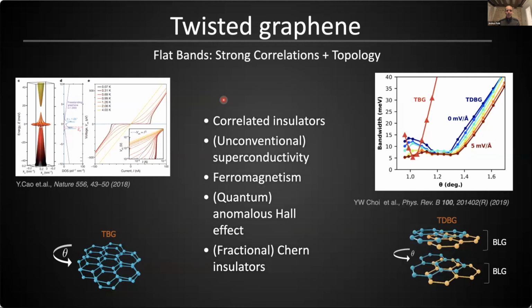But the special feature of twisted double bilayer is that because you don't have simply a single set of AB sites, you now have two offset. Then by tuning the vertical electric field, so the electric field across the bilayer of graphene, you can change the original band structure from being two hyperboloids that touch to flattening out the place they touch and creating a gap, and you get this Mexican hat geometry eventually.